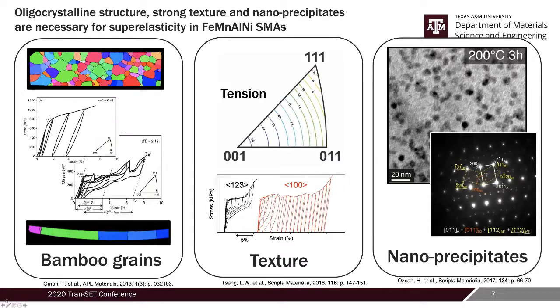Then you start to see that superelastic response. So it's extremely important that you manipulate the microstructure and obtain the correct microstructure. Also, these materials are very anisotropic. That means that if the orientation of the grains is different, you can get a different response from the material. If your grains are oriented in the 1 2 3 direction, you get this nice superelastic response. In the 1 0 0 direction, you get a more hysteretic response.